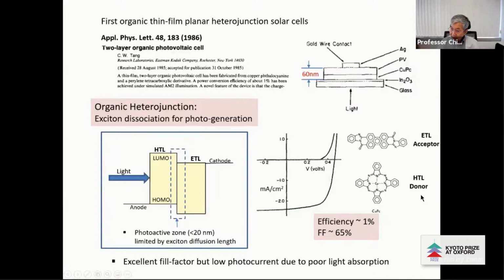I used the copper phthalocyanine still as the donor, but then I used a very strong absorber, the perylene tetracarboxylic derivative, as an acceptor. With these two materials, and making sure that the layer thickness is thin enough that they do not present enough resistance to impair the cell, I get a very efficient device, and particularly the fill factor. So the key here is that the junction between the donor and the acceptor is the key for charge generation. In this case, the exciton generated either in the donor or in the acceptor would diffuse towards the junction, where it separates into electrons and holes and then moves on to the respective electrodes.